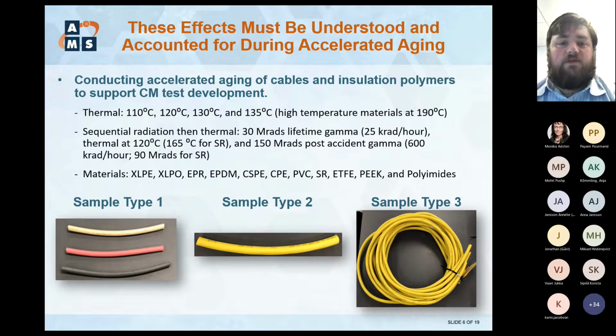We're doing high temperature materials like ETFE, ethylene tetrafluoroethylene, PEEK, and Polyimides and silicone rubber at higher thermal only temperatures, at 190 Celsius. And then, as I mentioned, we have a project going on right now where we're looking at conducting sequential radiation, then thermal exposures of a few different materials, including cross-linked polyethylene, cross-linked polyolefins, ethylene propylene rubber, and a few. A lot of the cables we have are jacketed with Hypalon or chlorinated polyethylene.